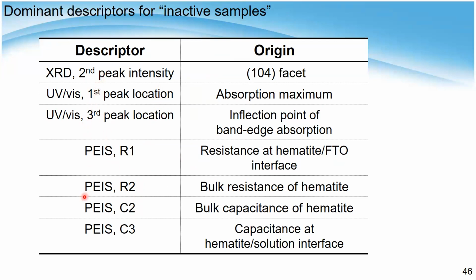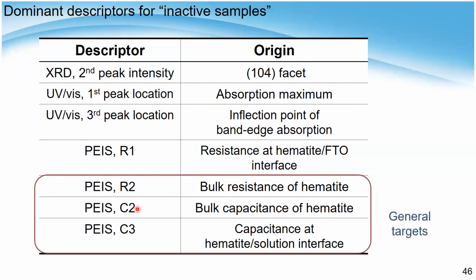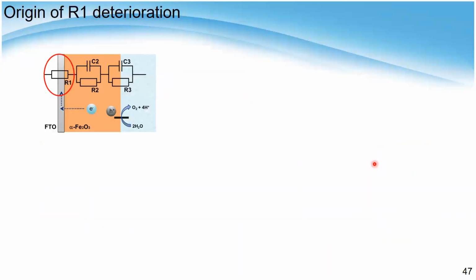Looking at here, the electrical properties are often selected. These R2, C2, C3 are general electrical properties, often used as general targets for improvement of the photoanode materials. So it's not much of a surprise. But then there is one value, the resistance between hematite and FTO, which is not much cared about in some research on photoanode materials, because it's a really general thing.